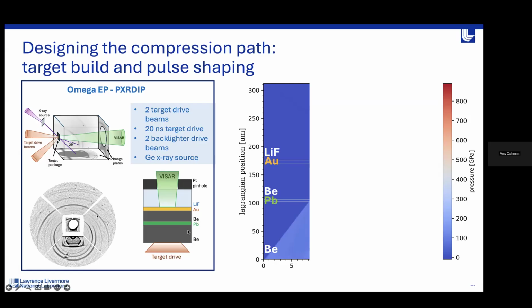What we have here in this target is our beryllium ablator layer, where our compression wave is launched. We've got a lead heat shield, and the purpose of this heat shield is to protect our gold sample layer from additional heating from the ablation plasma generated at the front of the target. We have a secondary beryllium layer, which acts as a nice spacer between our sample and our very hot heat shield.